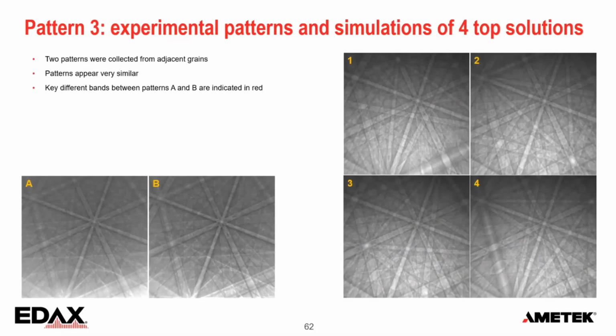And based on that, you can nicely identify the orientation. And these were the more critical ones. It looked like twin lamellae or twin boundaries here. And here on this image, if you look at all the main bands, the patterns are identical. But if you look a bit more carefully, you can see here a faint white band, a narrow one. And here's another one. That doesn't happen here. Here, that band goes through there, for example. And there's one going horizontal, which is not present here. So there is a very small difference